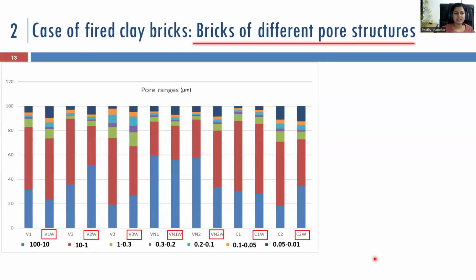Now we go to the second case study, which is fired clay bricks. These are all porosity data of different fired clay bricks of different porosities. What you see here in the histogram for one sample, for example V1, out of 100% porosity, we have divided it into porosity of pores of different size ranges.